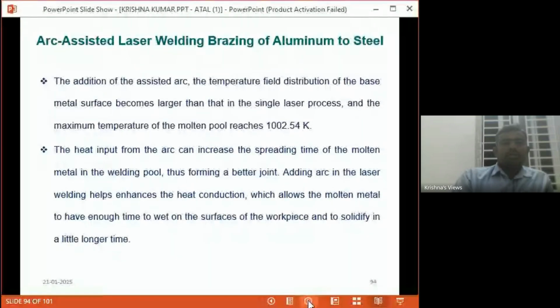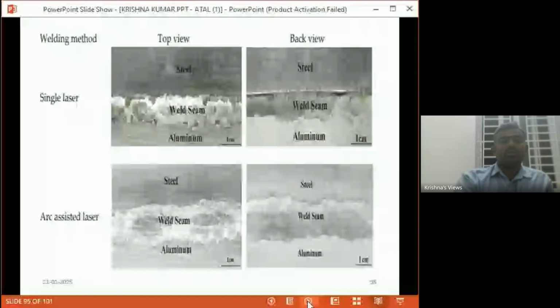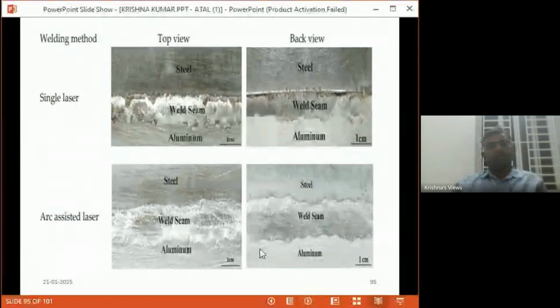So it's called arc assisted laser welding, brazing of aluminum to steel. So with the addition of the assisted arc, the temperature field distribution of the base metal surface becomes larger than the single laser process. And the maximum temperature of the molten pool rises. So we are raising the pool temperature. The heat input from the arc can increase the spread time of the molten metal in the welding pool. That helps us. So there are two comparisons, single laser and arc assisted laser.